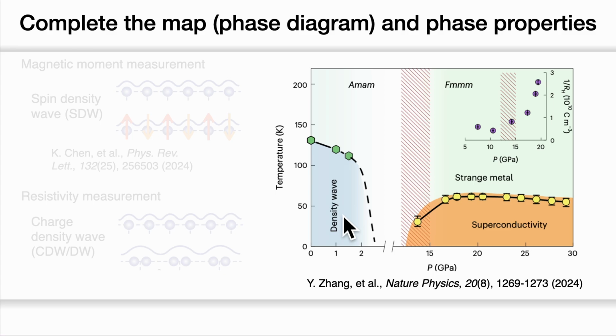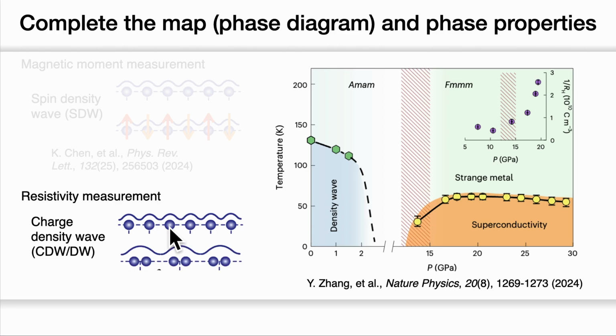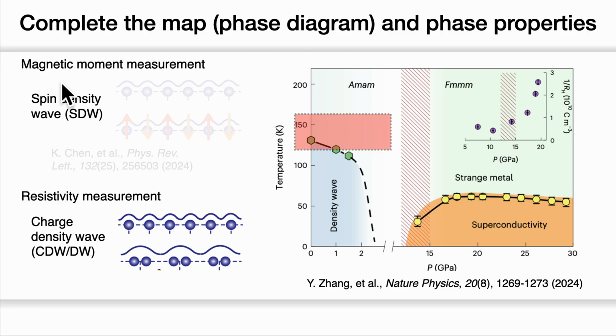Understanding the phase diagram and the microscopic pictures of these phases is important to manipulate the superconducting phase. From the resistivity measurements, the density wave is believed to be a charge density wave, CDW. Charge density wave can form due to electron-phonon interaction rearranging the ions. However, another experiment measuring the magnetic moment of the density wave shows that this density wave might coexist with another density wave called spin density wave. Here we call it SDW.